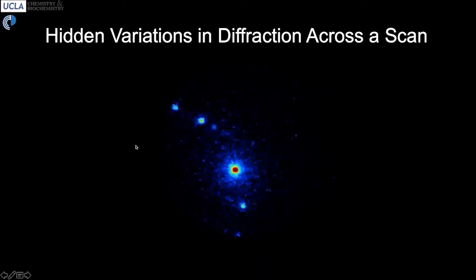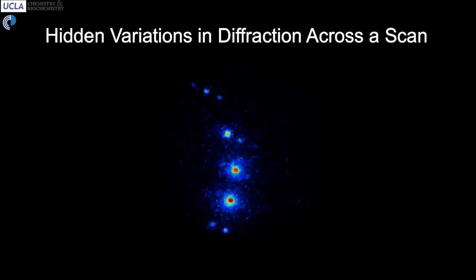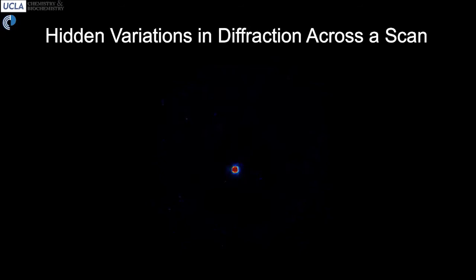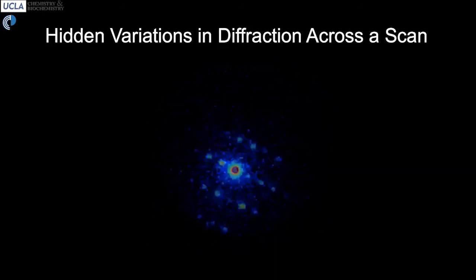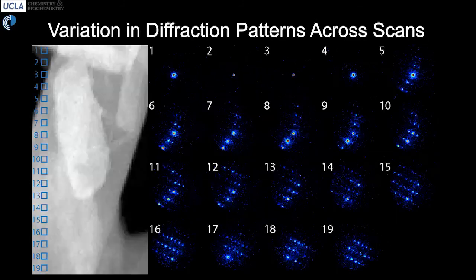And so what we realized is that maybe our control samples weren't really behaving like control samples. And we were really interested in trying to understand, well, what type of variability can we see not only with control samples, but with real samples, and can we make something out of this? This variability is best understood if you look at an image of the crystal that we were interrogating. So this is a rod-shaped crystal. You can see the rod here sort of going diagonally across the viewing area. And you can see it's sitting on a piece of lacy carbon.